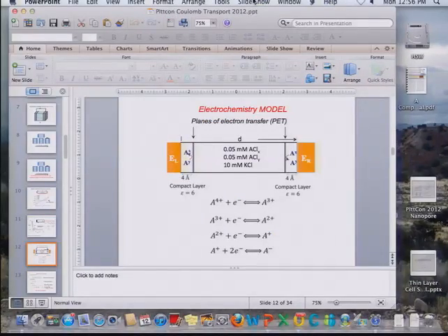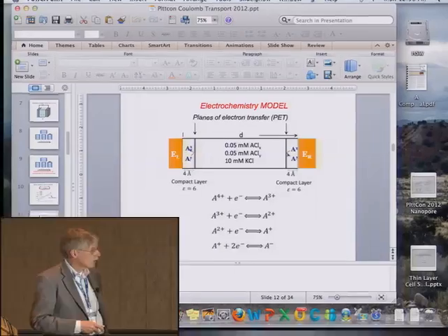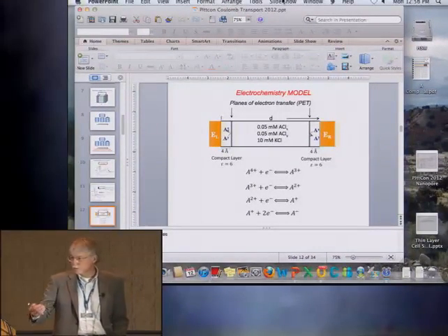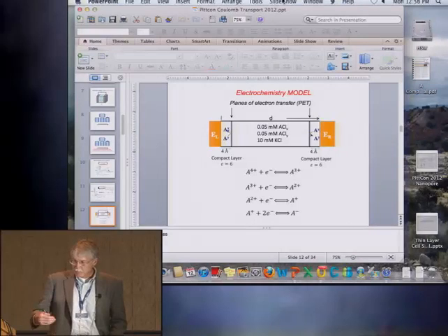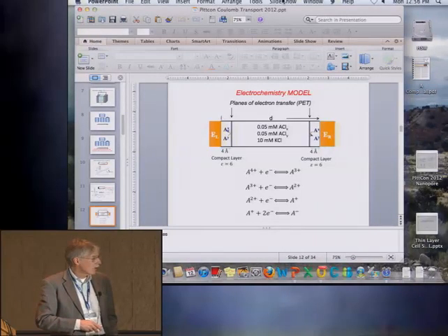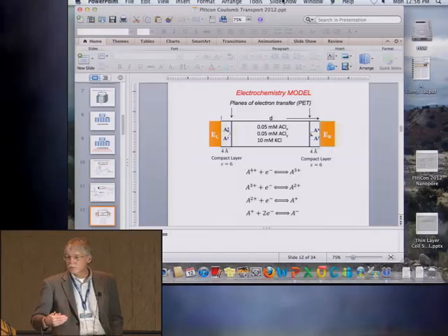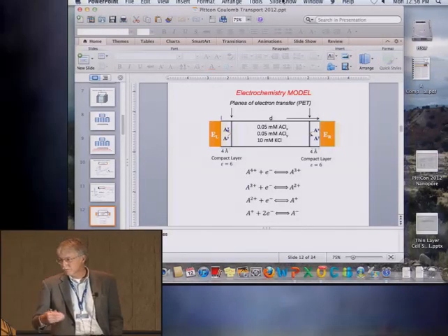Okay. So now the electrochemistry, that was the potential profile. The electrochemistry is the same cell. We're going to have redox species, the oxidized and the reduced form, and here are the equations, the redox chemistry. I'll go through one of these in some detail. I don't want to get into too much of a description of the calculation. You do have to put in a plane of electron transfer at these interfaces that corresponds really to the closest approach to the redox molecule. You have to put that in and then put in a reasonable dielectric for the solution adjacent to that charged metal surface. So for water, it's about 5 or 6, and we use that.